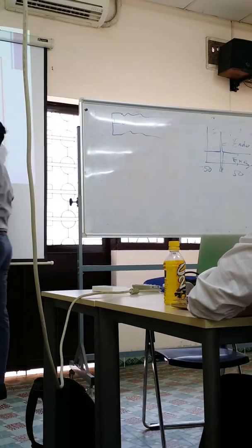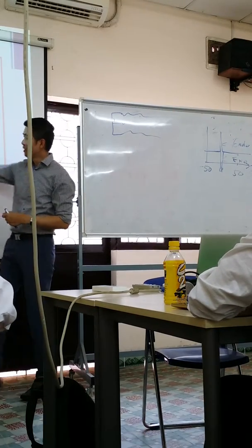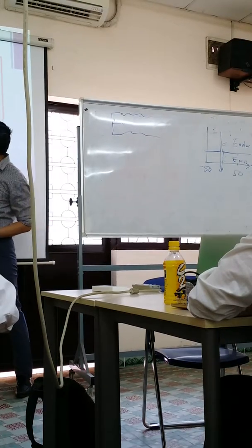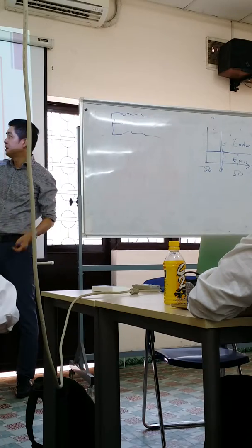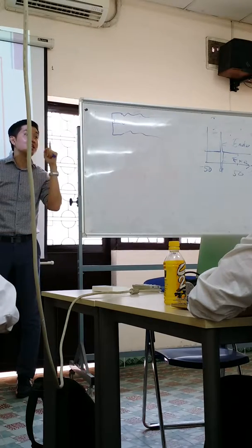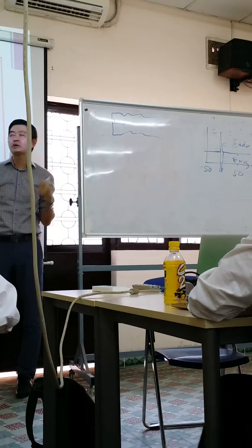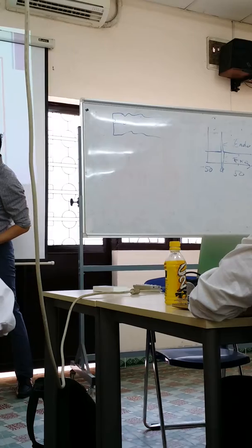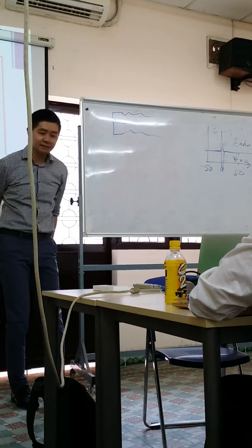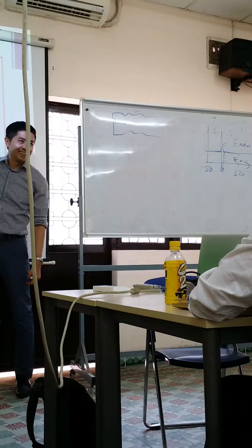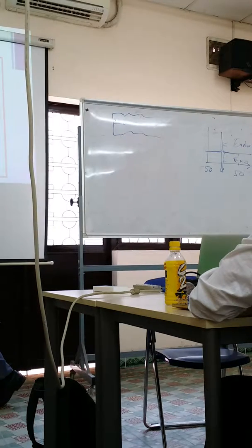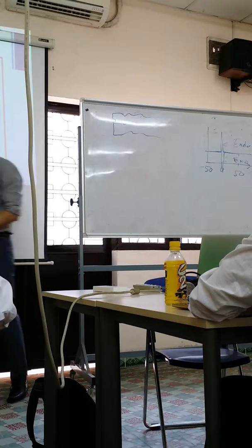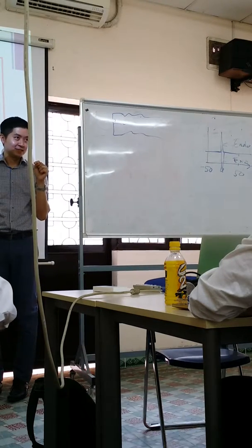Beta 2, this is one chair, right? This is another chair but opposite direction. One chair referring to one TAG. Do you get me? Okay. So when there is this way of arrangement, very close, the one that you sit close to each other, this one we call 2x. 1x, one fatty acid, 2 fatty acid, 2x. Is it clear?